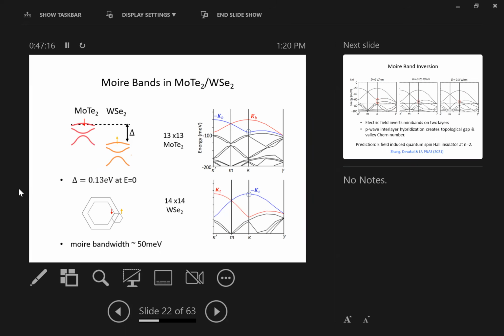Yes. Okay. So just to clarify, both the Mott phenomenon and the charge transfer phenomenon include these 2 layers. That's right. The single layer is just boring. But it's an excellent question. So Mott physics happens when charges are still mostly in one layer, but you still need a second layer to introduce a lattice corrugation so that it forms Moiré bands. Moiré bands have a smaller bandwidth. If you have a pristine monolayer, the bandwidth is very large. It's like a few electron volts. Then there's no Mott physics. Yeah, that's an excellent question.